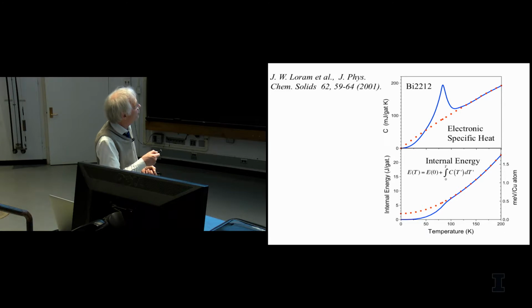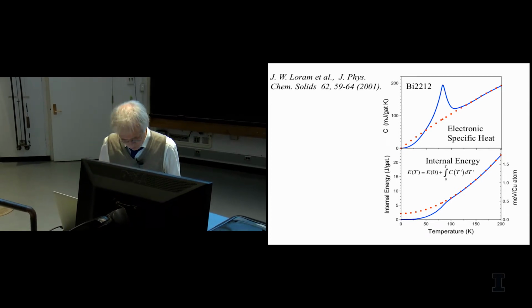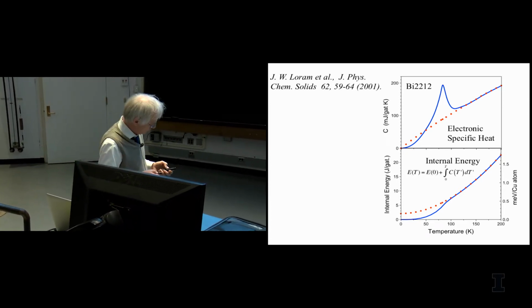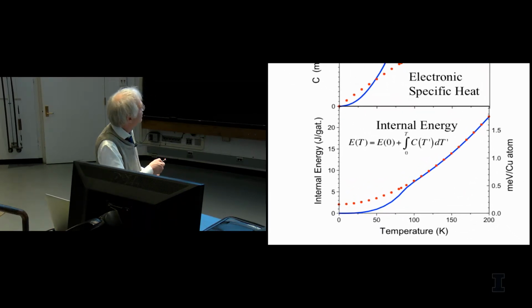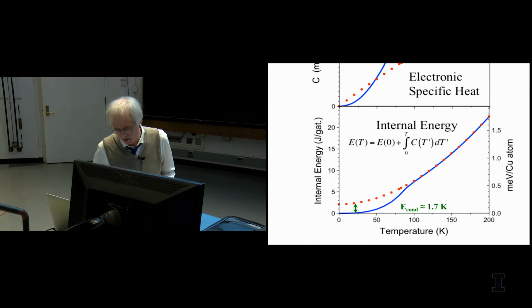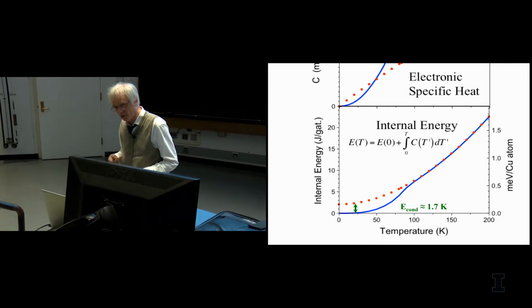Here is an optimally doped sample from LSCO, and what is shown is the specific heat itself. Again, calculated is the entropy from it. And you can also calculate, sorry, not the entropy, this is the internal energy now, the integrated specific heat. And what's shown, the dotted line here, is the extrapolation of the normal state by satisfying certain entropy balance constraints. If you follow that extrapolation and you look at the difference between what it is here and what it would be if the system would not go superconducting, this difference is called condensation energy. In this particular example, it's 1.57 Kelvin per copper atom.